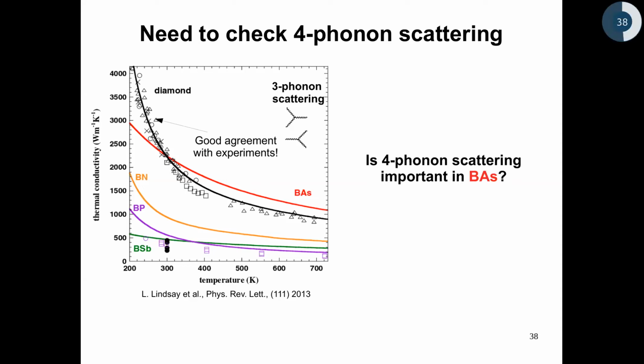So the fundamental question that I wanted to address is to estimate or actually quantitatively calculate the effect of 4 phonon scattering on thermal conductivity of boron arsenide. So before I show you some results, let me just give you a flavor of how challenging this computational work is to calculate 4 phonon scattering. So the problem boils down to actually just calculating the scattering rates. So if you have the scattering rates including 4 phonon processes, you can eventually get the thermal conductivity with very little work.